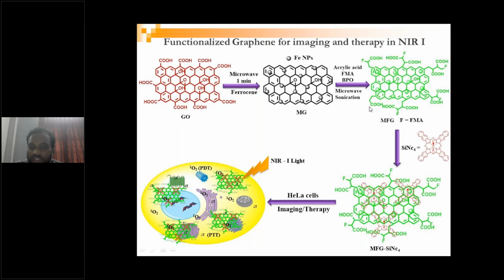And in order to go for fluorescence imaging, we functionalized with fluorescent methacrylate. We add acrylic acid, fluorescent methacrylate, and BPO, which is a radical initiator, under microwave sonication. These two monomers will functionalize on top of the graphene. As a result, we got magnetic and green fluorescent water-soluble graphene, also called functional graphene or multifunctional graphene. And this material is good for imaging and photothermal therapy.